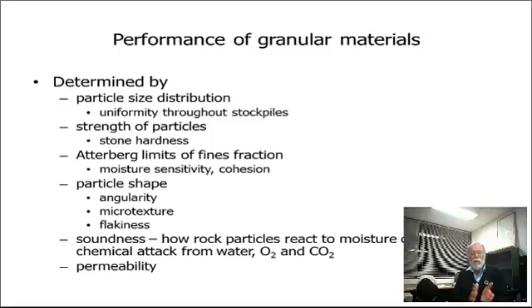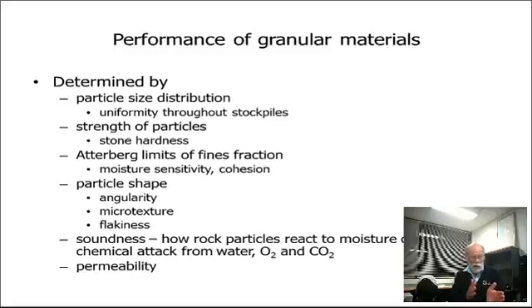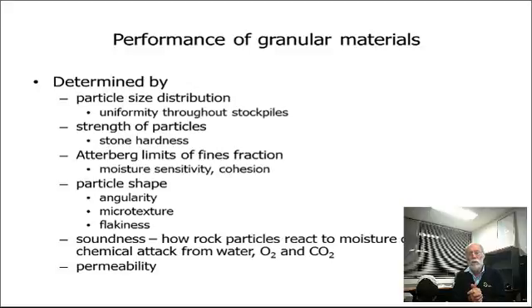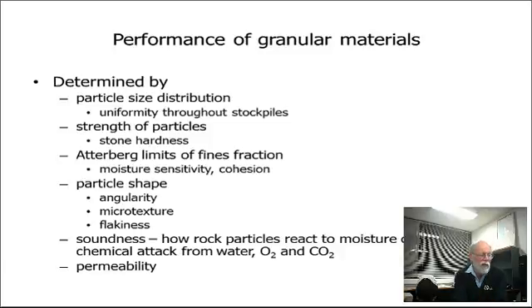The performance of granular materials depends on the particle size distribution, but certainly a lot on the uniformity of the material and the strength of the individual particles. There was a quarry producing road base out Meckering way — it was a granite but very friable with a very high LA test value. It didn't produce a good road base at all. Certainly stone hardness is important.